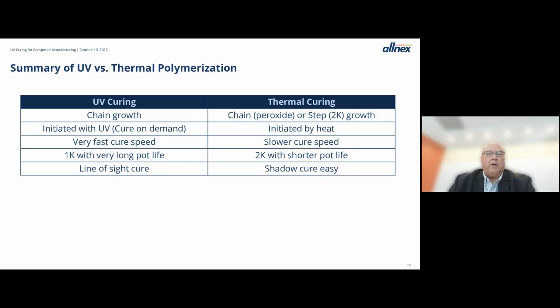So if we just take a quick look at UV versus thermal, UV is usually a chain growth process. Thermal can be either chain or step growth. UV is initiated with UV, obviously, and thermal curing is initiated through heat. UV is very, very fast. Thermal is generally slower. UV curing is single component with long pot life. Thermal curing is generally two component with shorter pot life if you count peroxide as one of the components. But UV is a line of sight cure, and you don't have that issue with thermal curing.